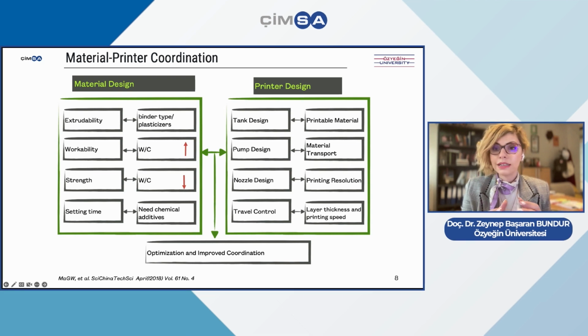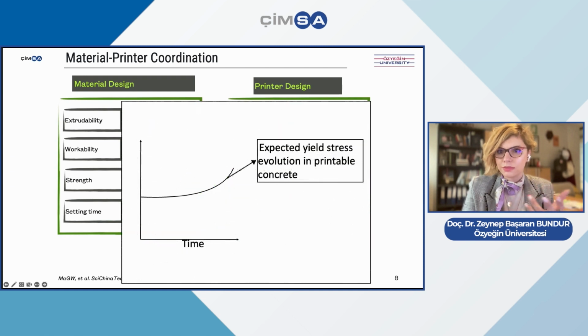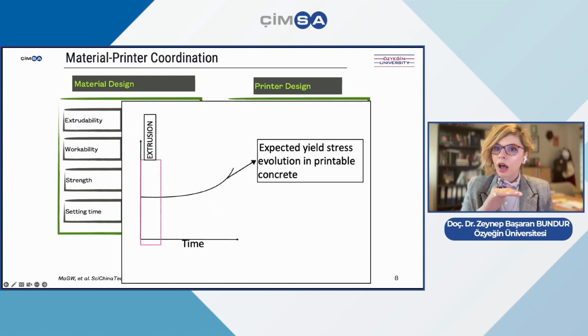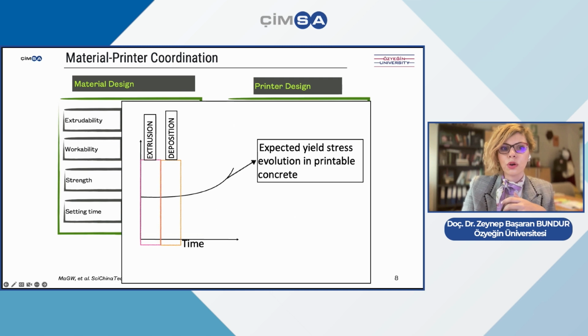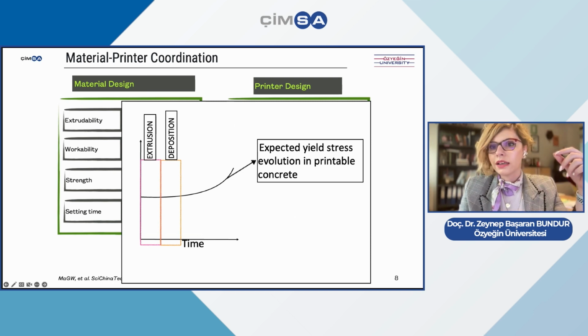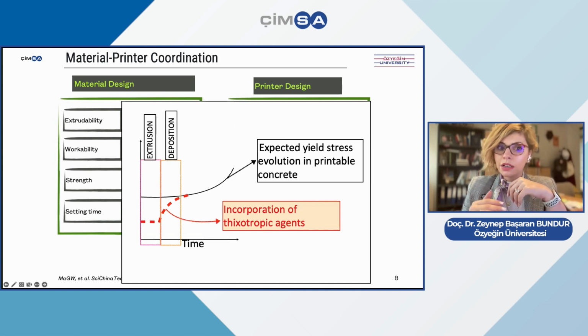Well, what about the speed of the printer and the alignment of the speed of the printer with the structure of the material? So we can have a material design for each printer, and we can adjust each printer for different types of materials. So in that sense, they're interchangeable. What's important here is that it's extrudable, so fluid enough to be extrudable, but it also needs to be workable. So it needs to have a basic strength initially, especially to have a strong basis and fundament. So it needs to be fluid until it comes out of the nozzle, and after it comes out of the nozzle, it needs to be printable layer by layer.